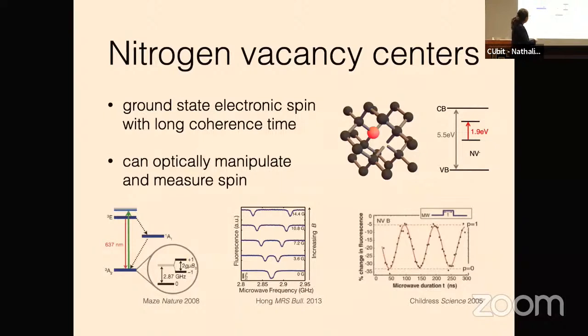So the negative charge state of the NV center is a spin 1 defect. So in its ground state, you have a spin triplet. And it turns out that there's this very convenient mechanism for reading out the spin state even at room temperature. So with very unsophisticated lasers, like basically my green laser pointer, I can shine light on this defect, and if I start in ms equals 0, I have a pretty good cycling transition, so it'll just keep on scattering photons and coming back to ms equals 0.